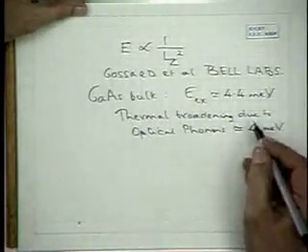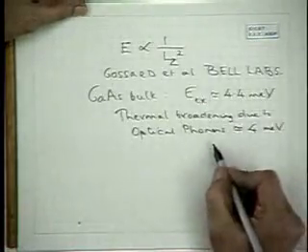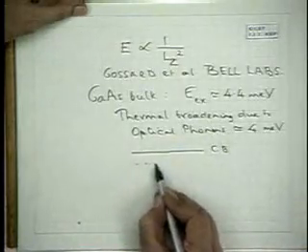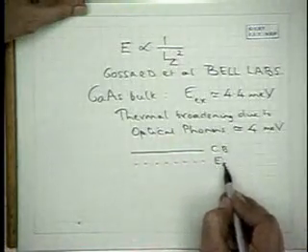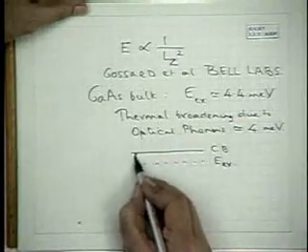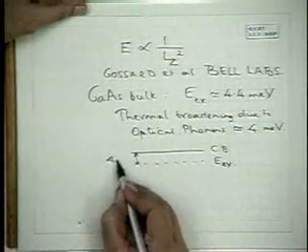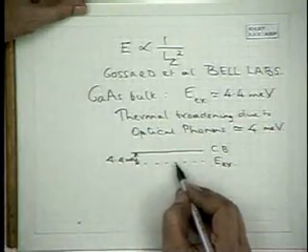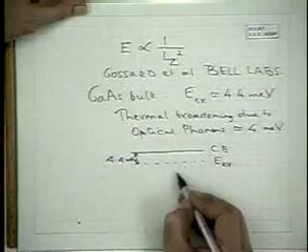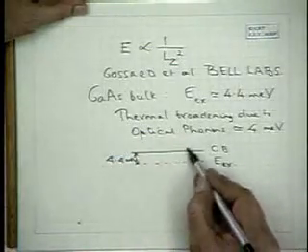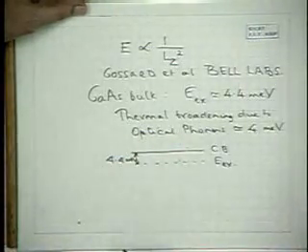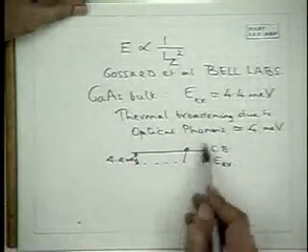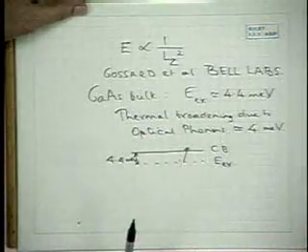Remember, kT at room temperature is 26 meV. So if you look at this conduction band, the fundamental excitonic energy is lower by only 4.4 meV. The electrons and holes can be easily broken up thermally, and you get a free electron and a free hole. And as a result, at room temperature, the excitons are not stable.